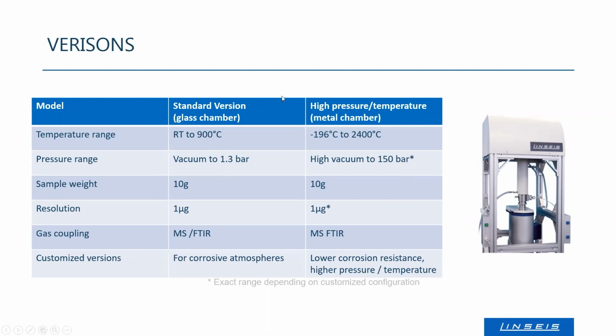We as a company offer two models, and what you need to know is we have a standard version, the one without a pressurized chamber, which is made for a temperature range up to roughly 900 centigrades, and it can run in vacuum up to 1.3 bar pressure inside of the furnace with a standard sample weight of 10 gram, which is, no matter which version you have, the sample amount you usually can measure with that kind of instrument, with a resolution of 1 microgram. It's possible to couple mass spec, FTIR, whatever to the gas outlet. I will talk about this later. And it's mainly made for corrosive atmospheres.